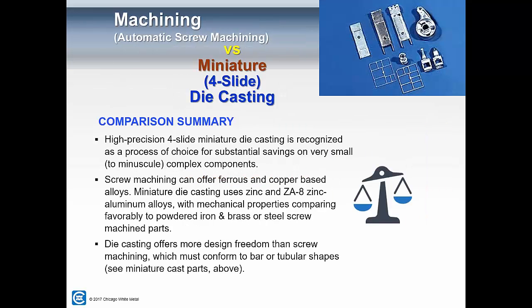And there's an example picture up on the right that shows miniature die casting. Again, it does very well with small parts, so it competes with screw machining, but it can also do geometries that would not be at all appropriate to be done with screw machining, as you can see from the pictures on the right. But it is essentially for zinc. If it works to do small parts in zinc, miniature zinc is definitely the way to go.